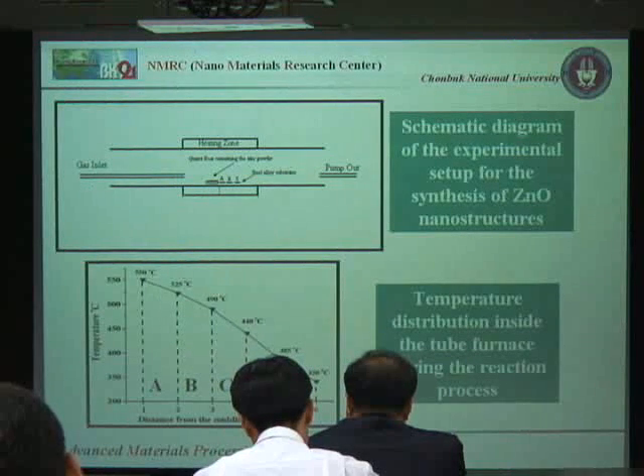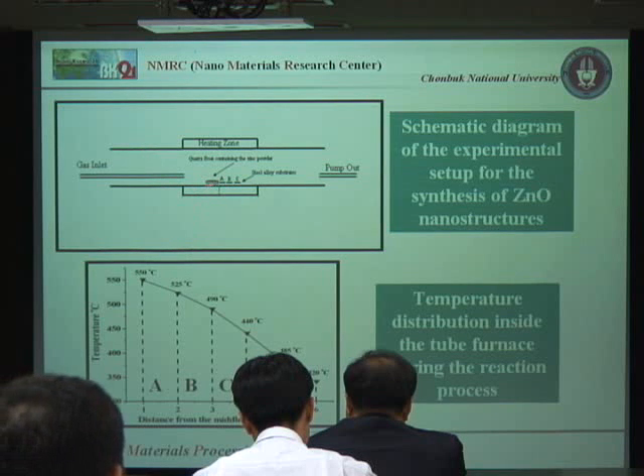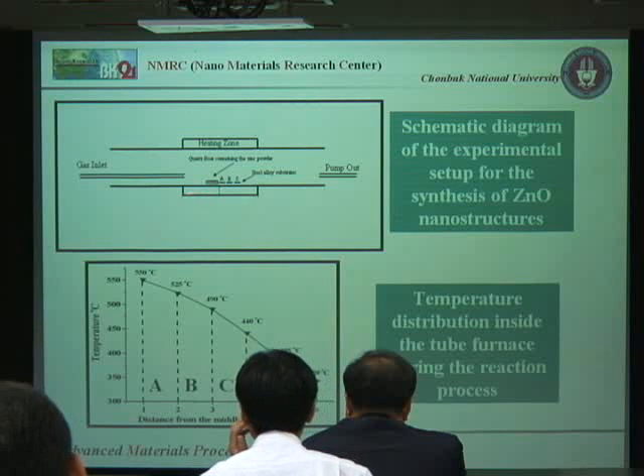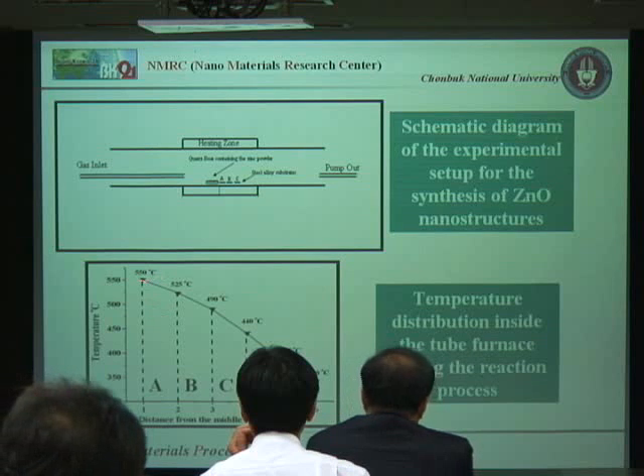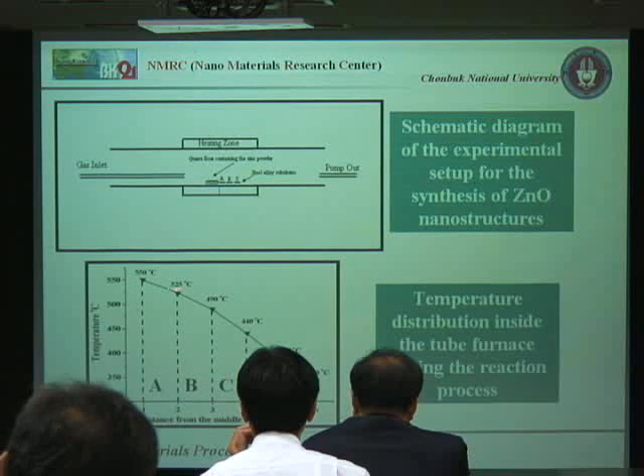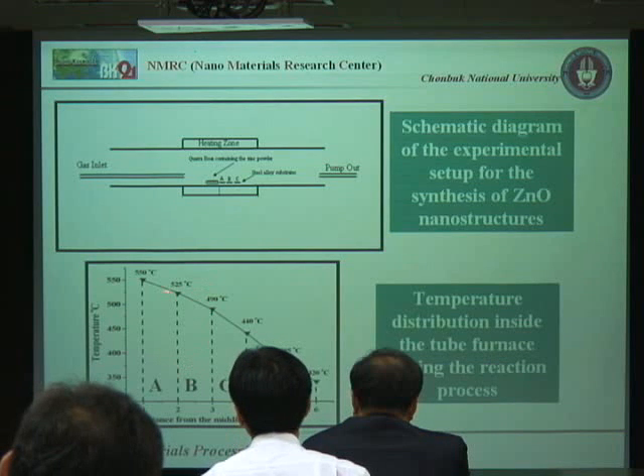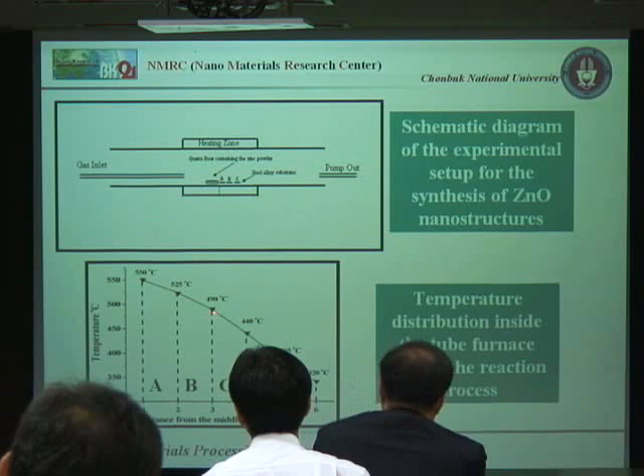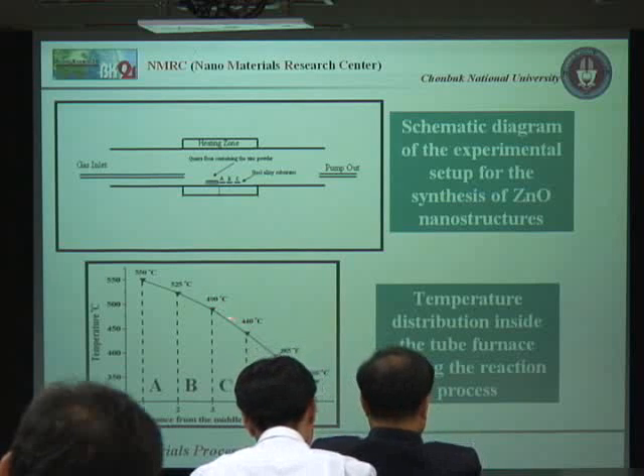This is our schematic diagram of the experimental setup which we use to synthesize our zinc oxide nanostructures. Here in the middle of our tube furnace, we placed a small quartz boat containing the metallic zinc powder, which we used as a source material for zinc in this synthesis. And we placed three substrates, indicated as A, B, and C, beside this quartz boat. During the synthesis, we observed the reaction temperature at each substrate. At each substrate the temperature was different. At substrate A, the temperature was 550 to 525 degrees centigrade, substrate B lies between 525 to 490 degrees, while substrate C lies between 490 to 440 degrees centigrade.